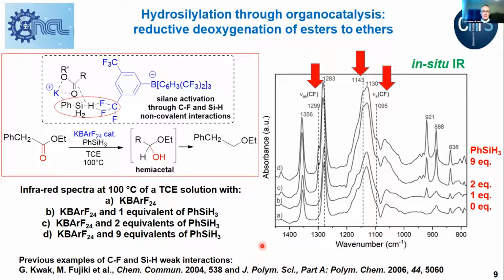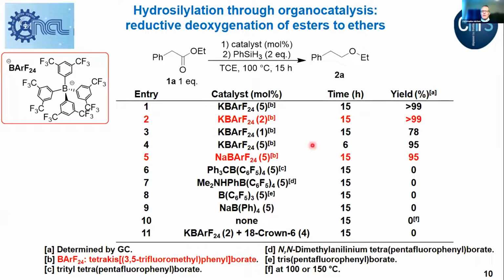Previously, evidence of such weak interactions with carbon-fluorine and silicon-hydride bonds was observed by Kwak and Fujiki in polymeric systems, but not involving borate salts. So just to go a little bit into details, as I said, potassium borate salt like this catalyst could be used for catalyzing such reductive deoxygenation of esters to ethers. This reaction proceeds with 2 mol% catalyst effectively and in almost quantitative yields in 15 hours at 100 Celsius. The reaction works also with the sodium borate salt, but a little bit less effectively. Other fluorinated borate salts or reagents were not effective catalysts for such a reaction.